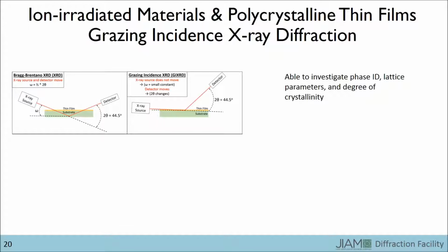As shown in the right panel, we can then hold the incident angle constant while the detector rotates through 2 theta, thereby keeping the penetration depth constant throughout the experiment. This is called grazing incidence X-ray diffraction. Our users regularly utilize this technique for phase identification, lattice parameter calculation, and the determination of the crystallinity of their samples. In a moment, I'll show you a real example of data collection from 40 to 50 degrees 2 theta using both Bragg-Brentano and grazing incidence configurations.